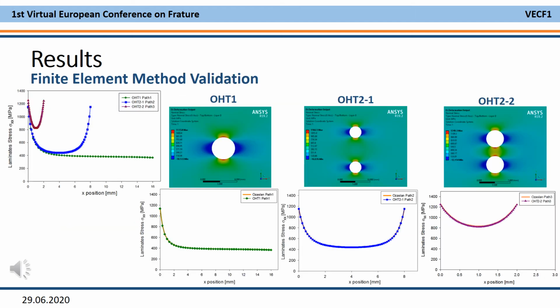Finite element method validation is done with Ozaslan et al. The validation is done separately for the three cases. On the laminate stress in x direction contour and on the laminate stress to x position figure, it's clearly seen that the holes in OHT2-2 specimen do interact. The maximum stress occurs on the hole edge for all cases.